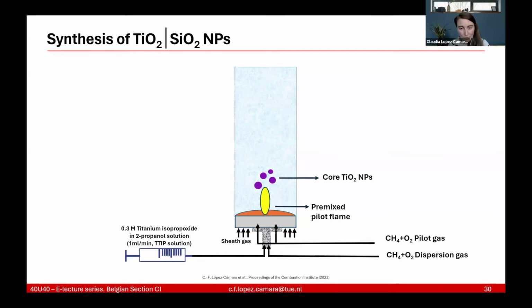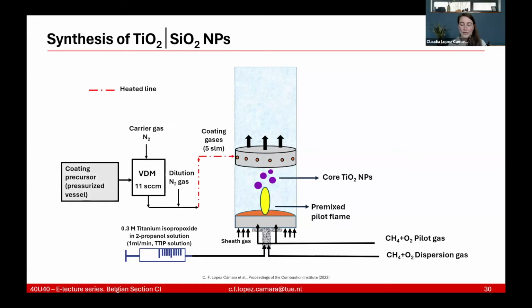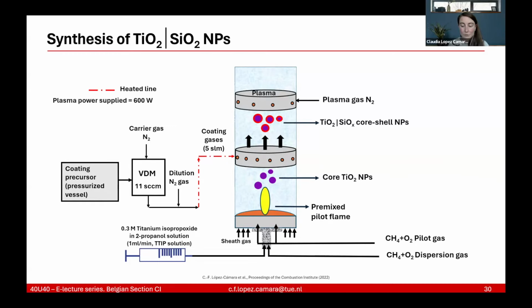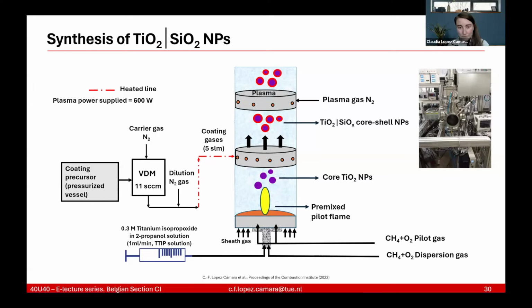So because we want to do coating, we then have coating gases. So we have basically jets surrounding the core flame that are inputting the coating precursor, different coating precursors that we tried for silica. And then you have the titanium silica nanoparticles afterwards. And the idea was also to try to avoid agglomeration of these core-shell nanoparticles, and that's why we included a plasma, which was the DBD plasma that I showed you at the beginning. And then you have the hopefully not as agglomerated nanoparticles at the end.